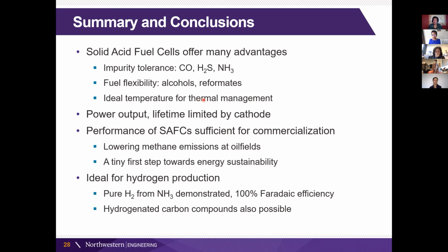Okay, so then to summarize, these solid acid fuel cells offer lots of advantages in purity tolerance. I didn't show you the sulfur tolerance, but it's also quite good. You can see that we can pass ammonia to that platinum, it doesn't mind. And if we have ruthenium, we're actually able to convert that to hydrogen. So we have good fuel flexibility and ideal temperature for thermal management. And I didn't describe to you our real challenge that we're working on, which is dealing with the cathode air electrode. There's some potential for commercialization going on. And again, as I said, we have this great way to produce hydrogen from ammonia.